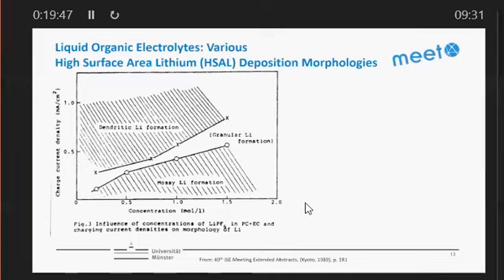And then on the y-axis, we see the current density during charge, and on the x-axis, we see the concentration of the salt. So basically, in the research that we are doing today, we look, for example, at the surface area to current density relations for structured lithium metal anodes, and we also work on concentrated, highly concentrated, or super concentrated electrolytes with a lot of salt or even only salt ionic liquids. So this is from 1989.